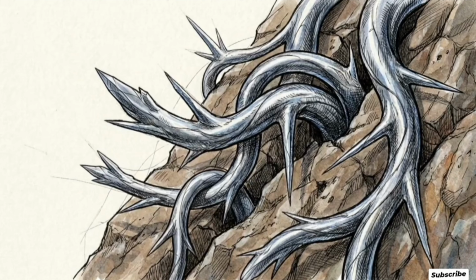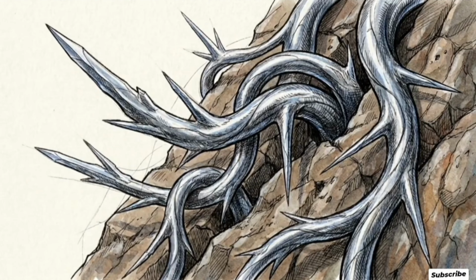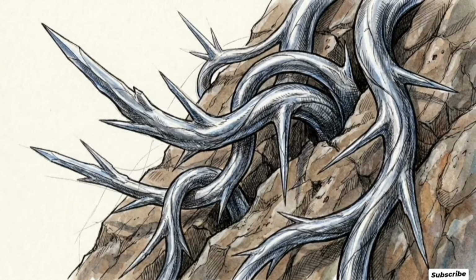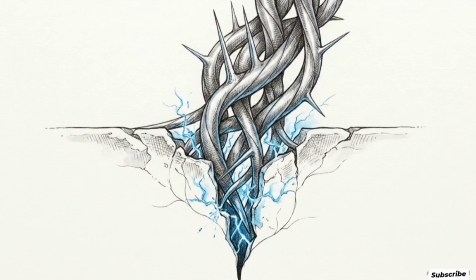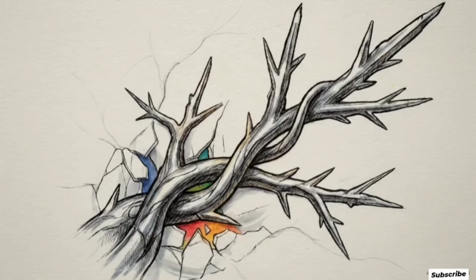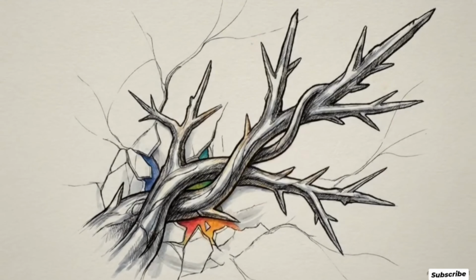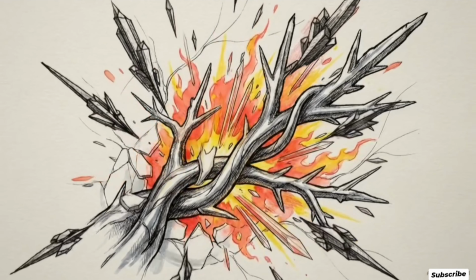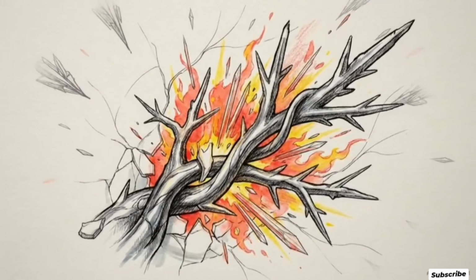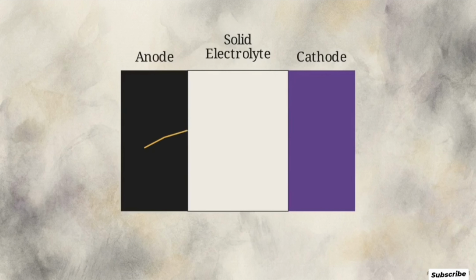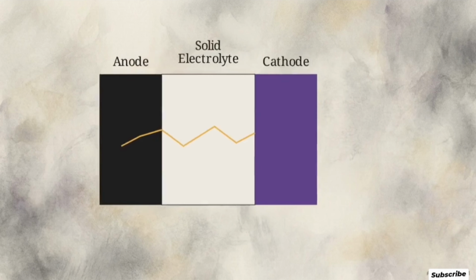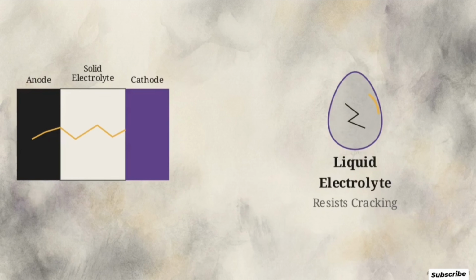They are opportunistic, exploiting manufacturing pores, weak ceramic grains, and mechanical microcracks. Driven by electrical current, these metallic vines force their way deeper through the electrolyte's compromised pathways. If a dendrite bridges the gap from the anode to the cathode, it creates a short circuit, leading to thermal runaway. While solid electrolytes were intended to block these filaments, rigid ceramics provide the exact crack pathways dendrites need to grow, a vulnerability liquid electrolytes don't share.